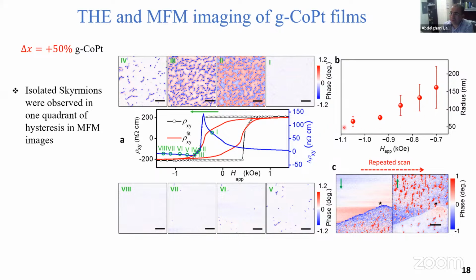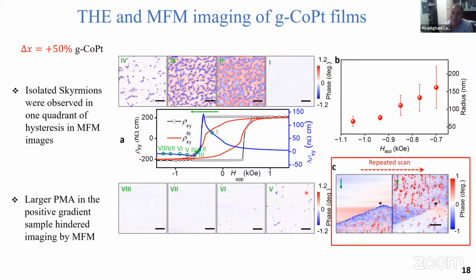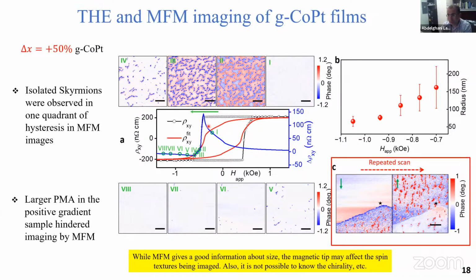The radius of these skyrmions can vary from 50 nanometers to 200 nanometers. The fact that this sample has large PMA, in particular on the positive gradient side, can lead the tip to some kind of artifact. For example, if we measure a scan here, we see nothing on one side, and then in the next scan you see spin textures. Because this has PMA, it has a very narrow topological Hall effect region. While MFM is very good, it gives information about the size and correlates very well to the topological Hall effect,